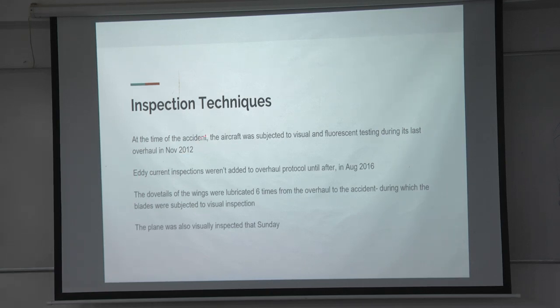So, fluorescent penetrant inspection. A lot of times the cracks are always closed, unless there is a load to open them. Whenever there is an accident or anything for that matter, the crack is very closed, and you have to look for it a long time. But instead, if you do FPI, fluorescent penetrant inspection, that's the first thing you should do always.